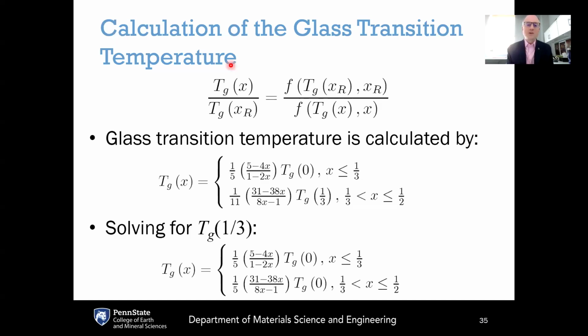According to temperature-dependent constraint theory, the glass transition temperature can be calculated through this evolution of the topological degrees of freedom, where if a system has more degrees of freedom, that actually lowers the glass transition temperature because it's easier for the atoms to move around. If the system has a lower number of degrees of freedom, that means it's more rigid, and that means the glass transition temperature increases. And so using this formula, we can calculate the evolution of the glass transition temperature as a function of the modifier content here, x, relative to some reference Tg.